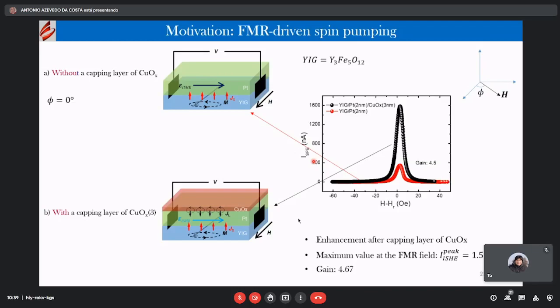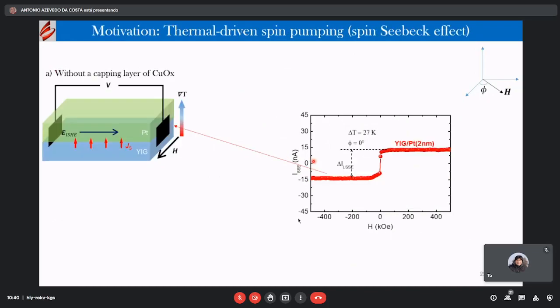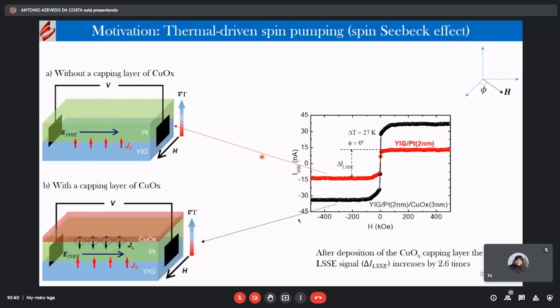So the enhancement after the capping layer of copper oxide cannot be explained easily. And we also measured the same samples using the thermal spin pumping, or spin-Seebeck effect. This is the spin-Seebeck effect curve just measured in yttrium iron garnet, platinum. As the field sweeps up and down, the magnetization sweeps up and down, and we measure the voltage here, which is similar to a magnetization curve. When we put copper oxide, we detected an enhancement. The enhancement is a little bit smaller, about half of the enhancement obtained by the spin pumping effect, but we also obtained a significant enhancement of the signal.